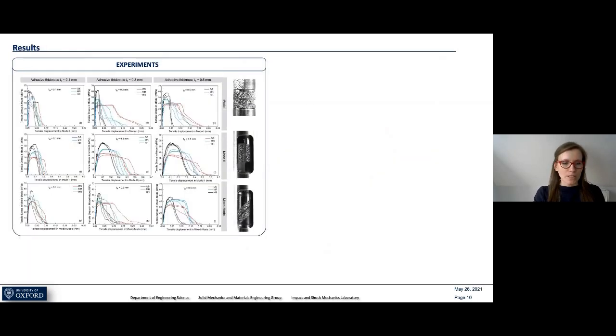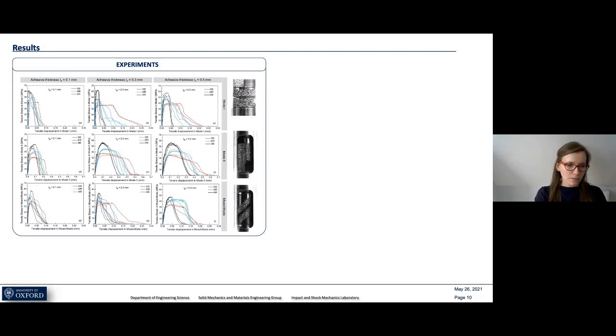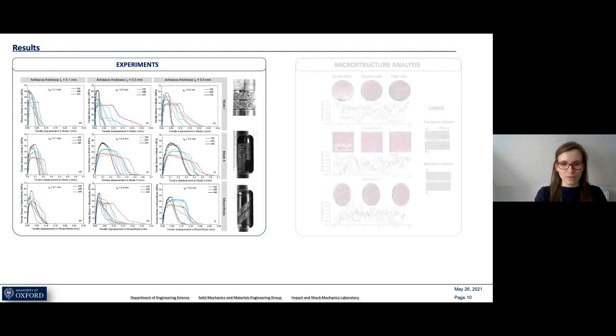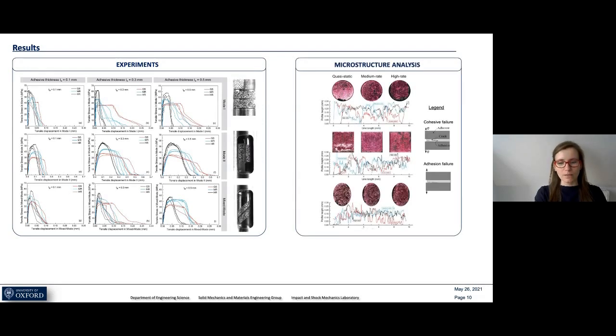Results from the adhesive interface tests are presented, where three different fracture modes — mode one, mode two, and mixed mode — were tested at three different adhesive thicknesses and three different loading rates. Before concluding the method and cohesive zone model are valid, the fractured surfaces were checked to confirm cohesive failure was achieved, which was the case. This confirms that the experimental methodology and the use of the cohesive zone model are suitable for further investigation.